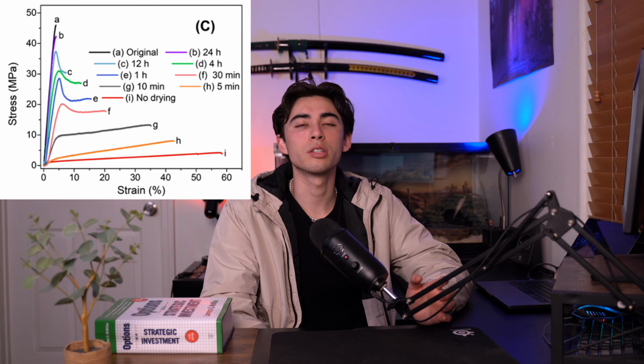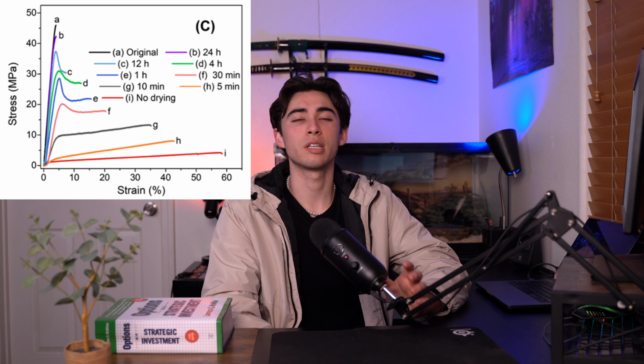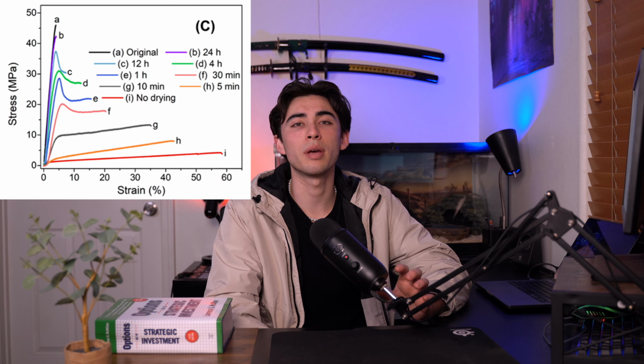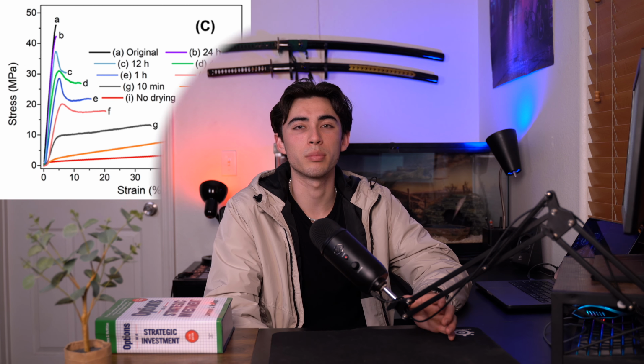After drying at 120 Celsius for 24 hours, the sample has a stress of roughly 42 megapascals and a strain of 4.1%. These properties of the fully dried sample with reformed imine bonds are comparable to the original sample.